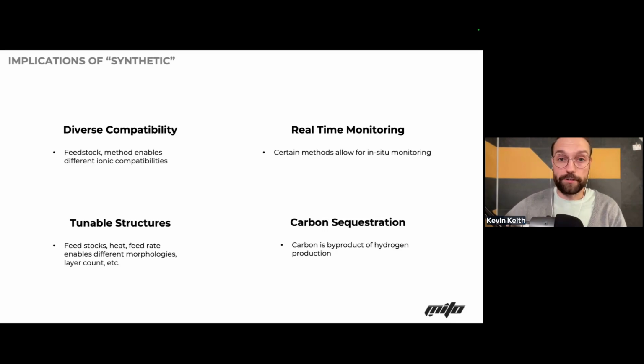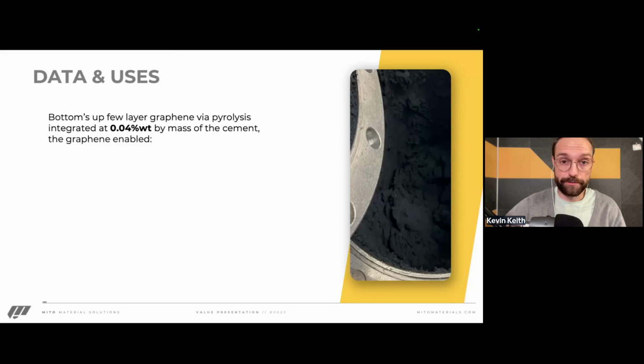ARPA-E, through the Department of Energy, did a whole study that in order to make hydrogen a viable fuel source and get the cost down, that solid carbon has to be commercialized. And it's not even a crazy amount. It's something like $200 a ton that it has to be commercialized at in order to cut the cost of that hydrogen in half. So really, on the other side of this pyrolysis method, cracking that methane, you're able to create this value-add product that can be put into composites and rubbers and cement to have a higher performing system or lightweight materials. It's a really interesting circular method, where you can start implementing these types of materials.